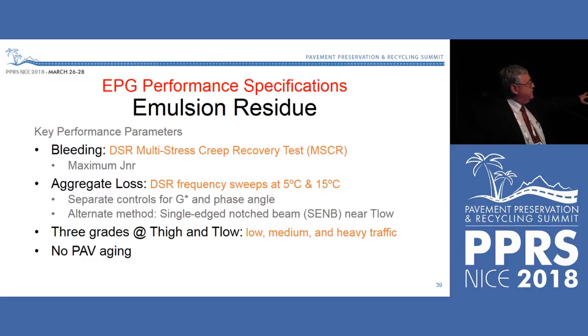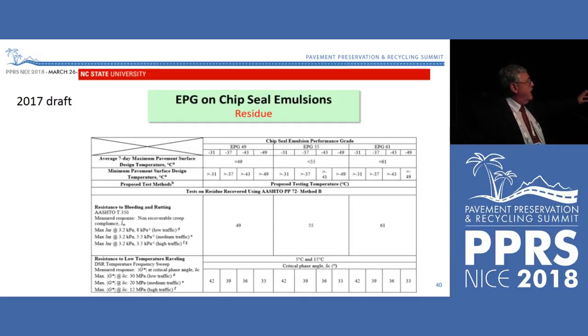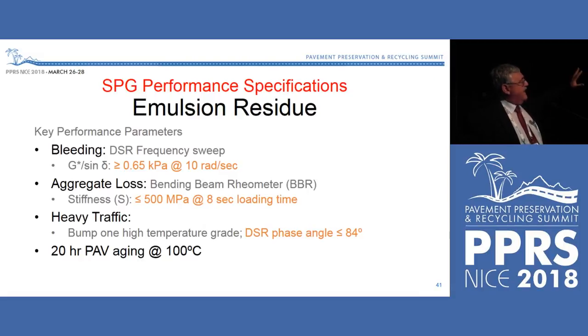In this case, for EPG, there is no PAV aging. And this is what the residue specification looks like. It's in the paper. I won't go through it. The SPG, the Texas work, they're looking at G-star over sine delta rather than MSCR. So they're using DSR for bleeding, but 2 different tests. Aggregate loss, they're using stiffness of materials, whereas the EPG specification initially used a single-edged notch beam and was looking at fracture properties. Now they're changing to rheological properties, but they're using the DSR rather than the BBR, and they're bringing phase angle and brittleness into the context where the Texas specification does not do that.